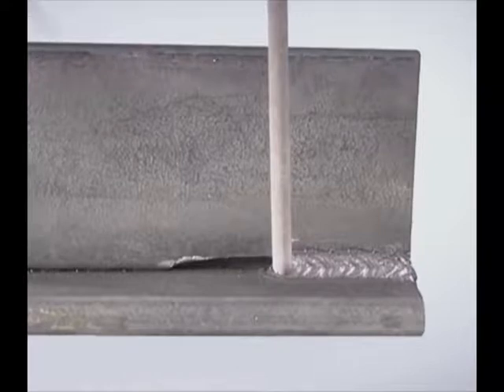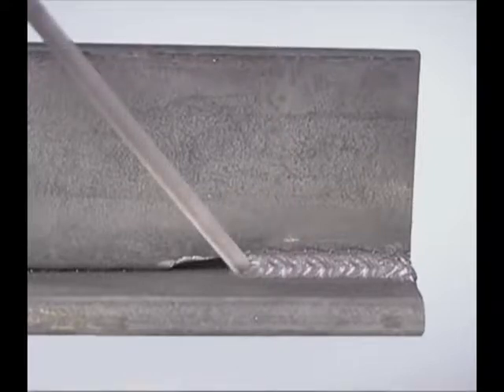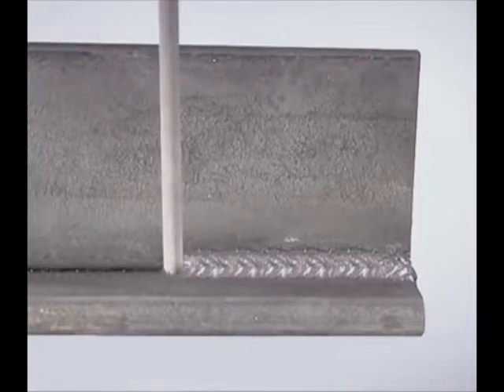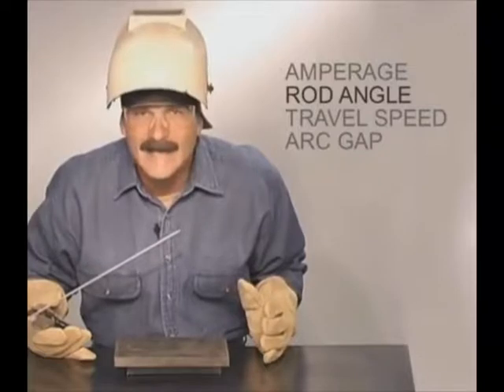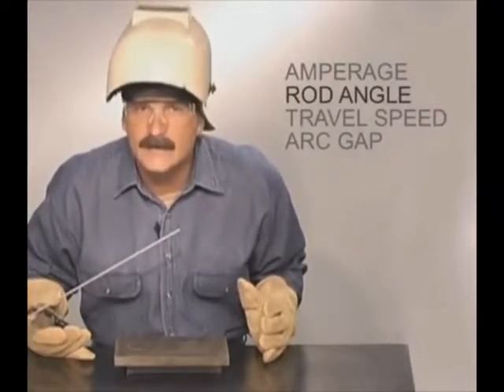On most weld joints with a good fit up, you want to maintain a consistent rod angle to produce a uniform weld bead. In some situations, though, you may need to vary the rod angle during the weld. To fill a gap in a weld joint, the rod can be angled more, slowing down to deposit more metal, keeping the build-up uniform, then angled back up to finish the weld. Controlling the rod angle takes a little practice, but you need to stay loose and relax. Whether you're holding the rod up to flatten the bead or angling it to build up weld, you want to travel at a speed that keeps the molten puddle the same size.